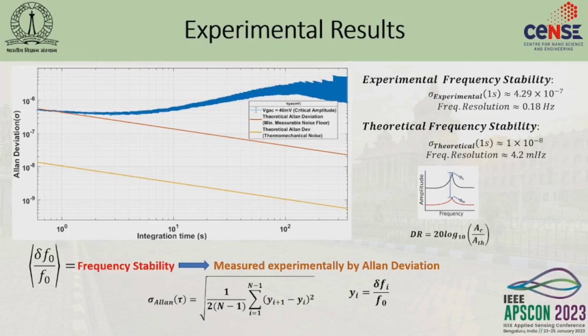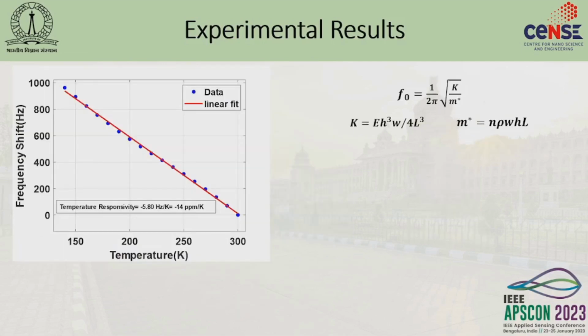So, after this, since we got this frequency resolution and frequency stability data, the next is the frequency response of the device. For the temperature sensing, we have performed the measurement in the cryo state, and you can see that as we decrease the temperature, the device frequency starts increasing, and the temperature responsivity, which is basically the slope of this curve, is about minus 5.8 hertz per Kelvin.